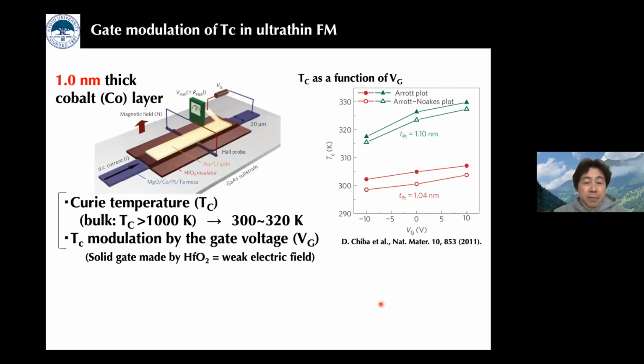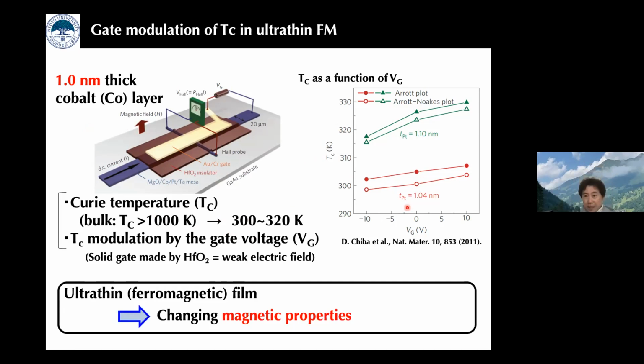Interestingly, a similar idea was also proposed by Teruo Ono's group in Kyoto. They fabricated an ultra-thin cobalt ferromagnetic film, and they also equipped a hafnium dioxide gate insulator on top of the ultra-thin cobalt film, and they tried to control the Curie temperature. The first important thing here is that the Curie temperature of ultra-thin cobalt is very, very low compared with the bulk Curie temperature. But more importantly and surprisingly, the Curie temperature of ultra-thin cobalt is modulated by the gating. So this means gating allows modulation of magnetic properties.